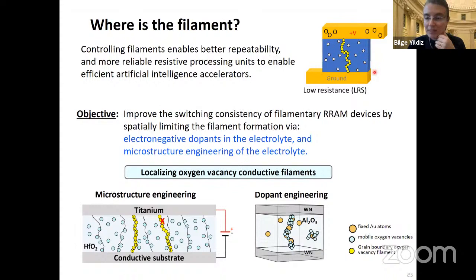So these are typically oxides that are deposited via different routes, that form non-uniform microstructures, that form non-uniform distribution of defects in them, that then gives rise to stochastic formation of these filaments. So you don't know where the filament is, and therefore you cannot control it. So what can we do? We are thinking of different ways to localize the formation of these filaments, either by engineering the microstructure or by engineering the chemistry.